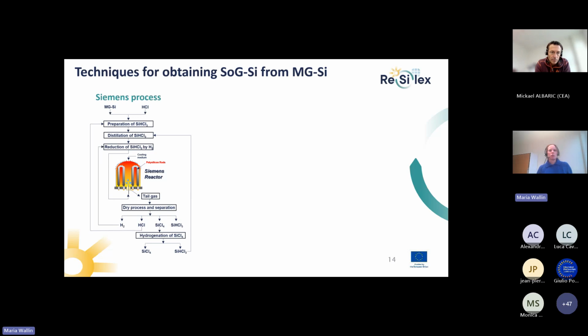So after you produced metallurgical grade silicon, what we also did in this process is to refine it to high purity. And there are different ways. The Siemens process is the traditional way, where you mix metallurgical grade silicon and react it with hydrogen chloride, produce trichlorosilane, and then you have to purify it, you have to distillate it, and then also you produce this vapor. So there's a lot of energy in this process. So it's quite energy intensive, but you get out very high purity silicon.